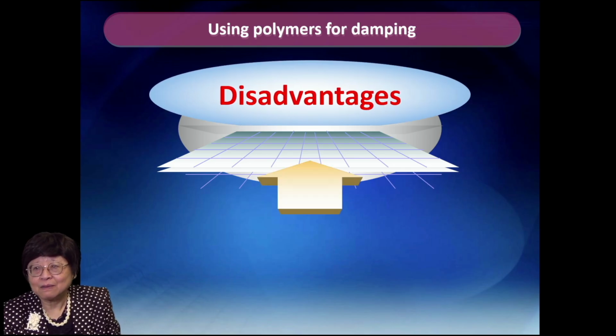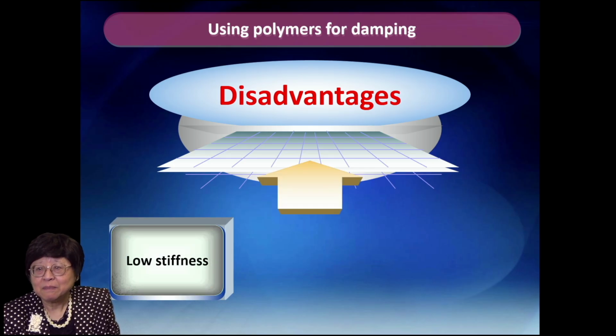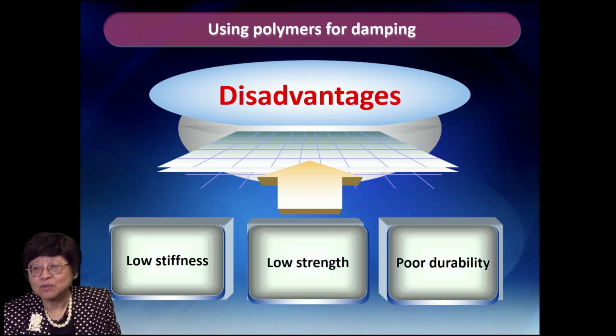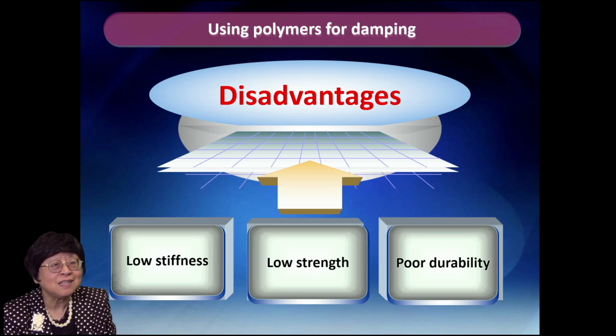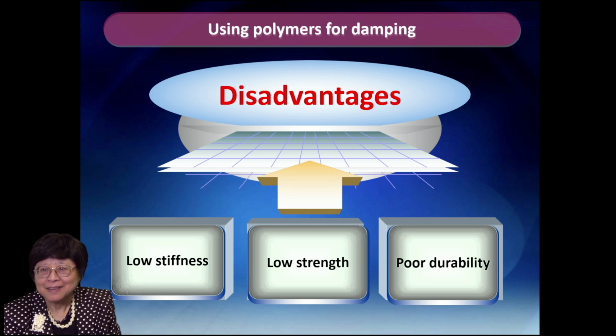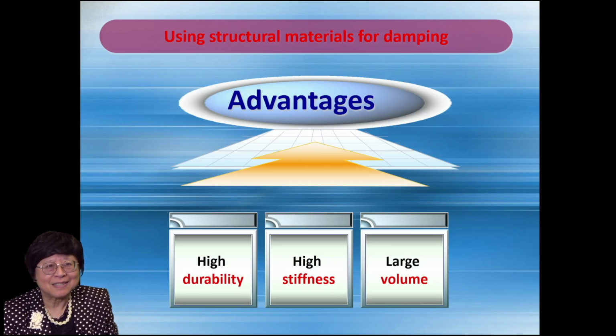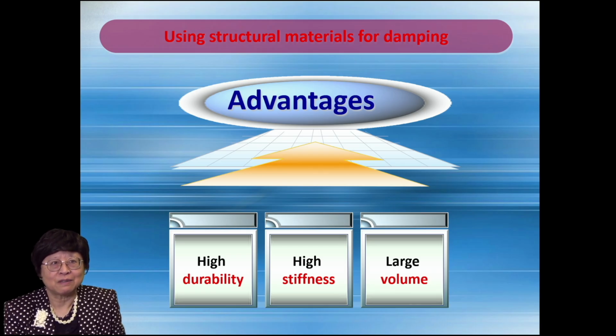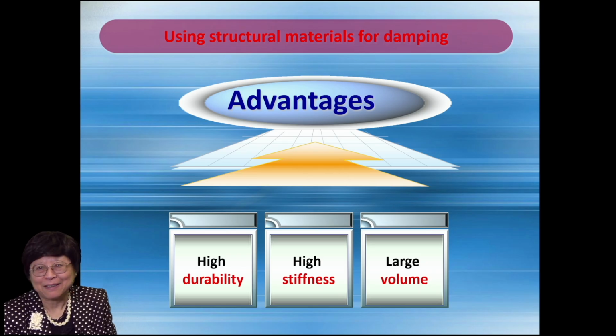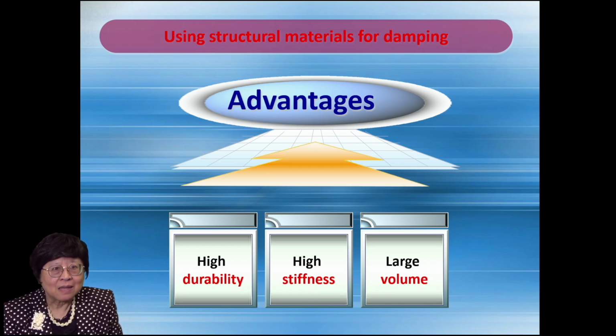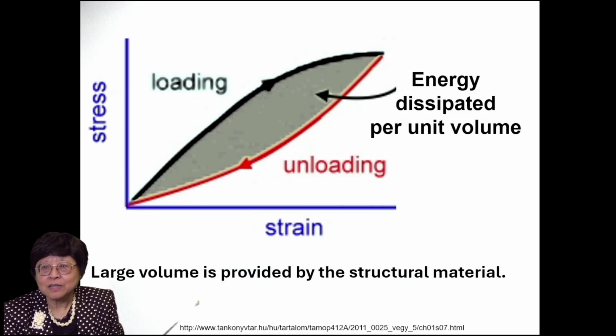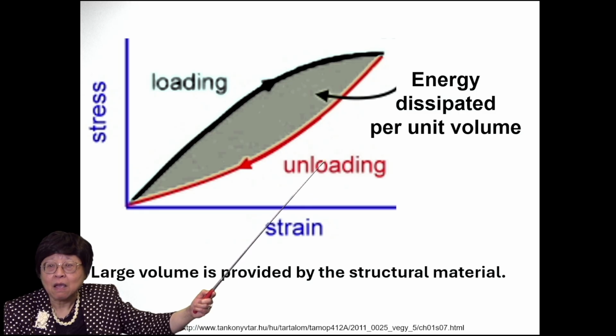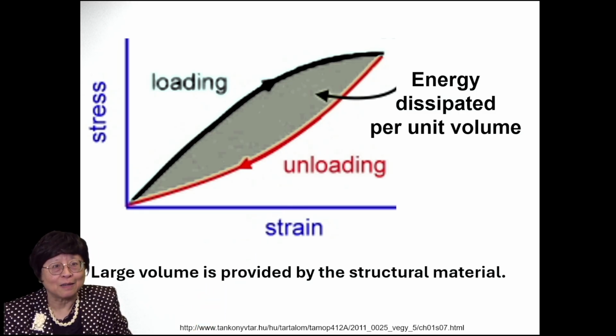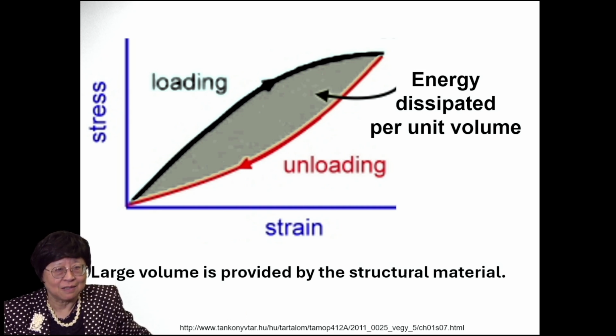Polymers like rubber are well known and utilized a lot for vibration damping, but there are serious disadvantages because they are low in stiffness, low in strength, and also poor in durability. Rubber bands cease to be elastic after maybe a month or two. However, my dream is revolutionary, using structural material for vibration damping. It's something that nobody has ever thought about. The advantages are high durability, high stiffness, and large volume. Now, the large volume helps a lot because this hysteretic area is the energy dissipated per unit volume. So if you have a big volume, it means a lot of energy dissipated, and the structure is big.